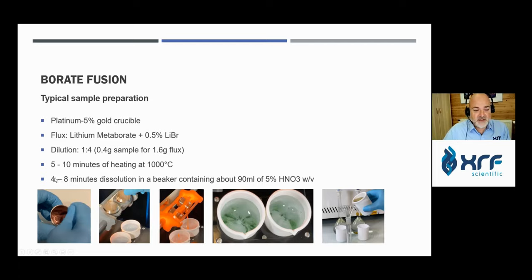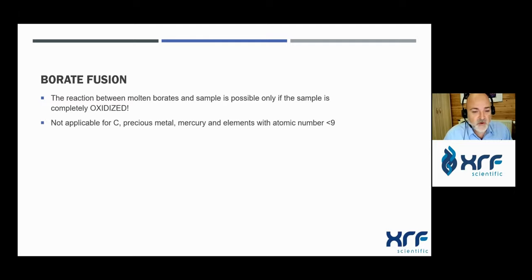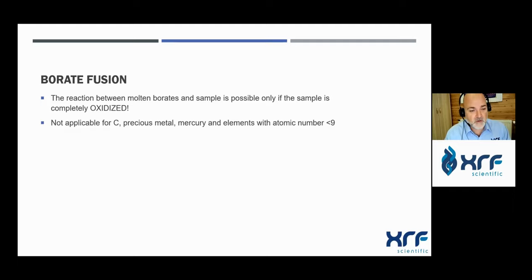An important point for borate fusion: the sample must be fully oxidized before dissolution in the borate flux — exactly the same requirement as for XRF fusion. If there are metallic samples or sulfides that are not fully oxidized, an oxidation step must be added. This type of fusion is not applicable for carbon, precious metals, mercury, and elements with an atomic number below nine.